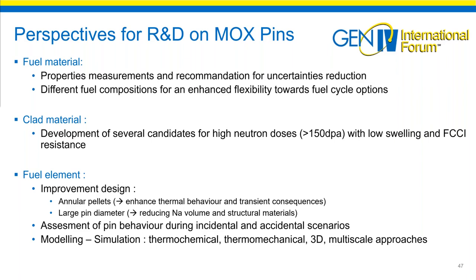Regarding the cladding materials, the achievement of high doses and the resistance to corrosion is a priority for the R&D program. Finally, the trend of pin design would be to increase the pin diameter in order to reduce the coolant volume and the volume of structural materials. And large diameters are also associated with annular pellet in order to reduce the maximum temperature during all the conditions. Improvements are also needed on modeling and simulation in order to be more predictive and to answer to the safety requirements for a reduction of experimental demonstration. An assessment of the pin behavior during the incidental and accidental scenario is also needed one more time for the validation of the fuel performance codes.